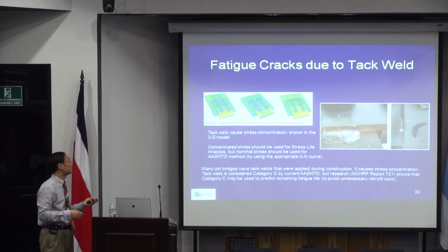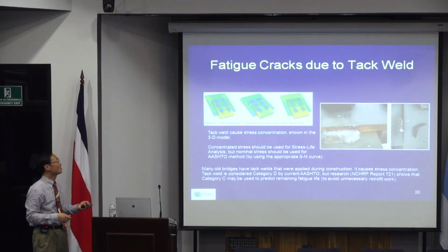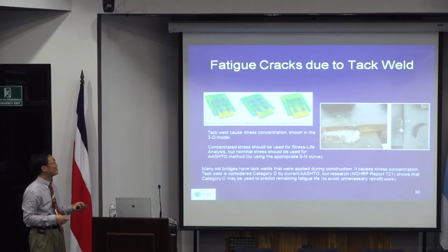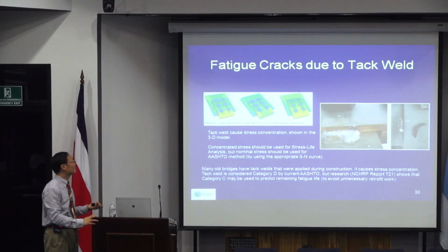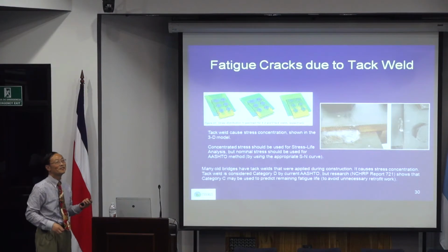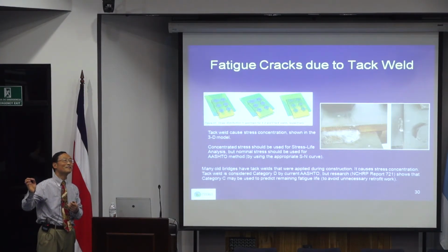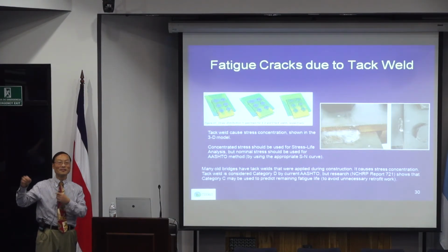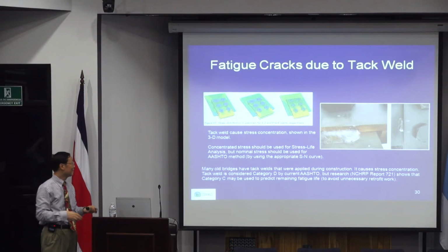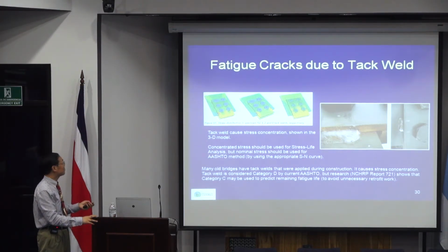And these things actually, they never remove that, so that causes stress concentration. And so that's why now it's not allowed. And now actually you don't need it because we have bolts. Bolts are relatively easy. You can put bolts in very quickly. But if you do have these, you should remove these. So actually, people did the finite element analysis, found the stress concentration for these is very, very large. That's why they have cracks.